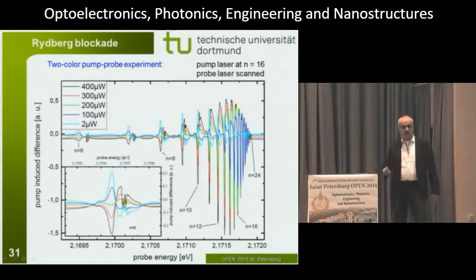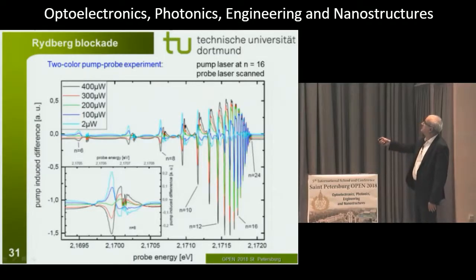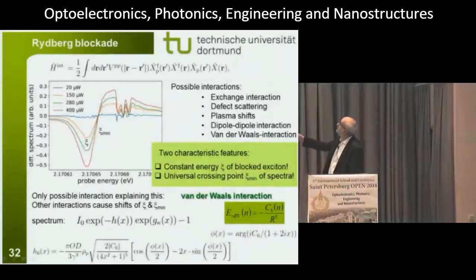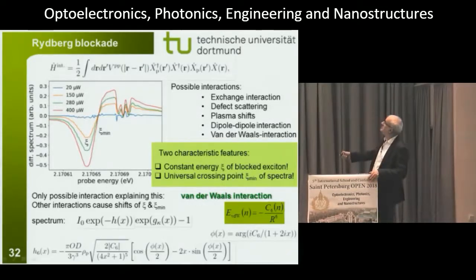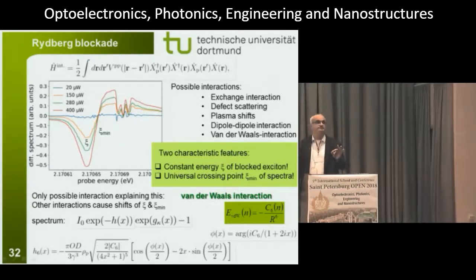Now you have to zoom into one of these sets of lines which corresponds to a particular principal quantum number. And there you find a very interesting behavior. This is basically the set of spectra that you record. In this case, it was the n equals 8 state for pumping at n equals 16. And you see that the energy of this line which becomes blocked does not shift at all. And also, what is very characteristic, all spectra show one point where they cross, irrespective of what pump power you are using.